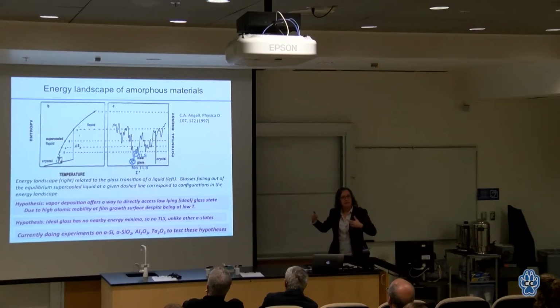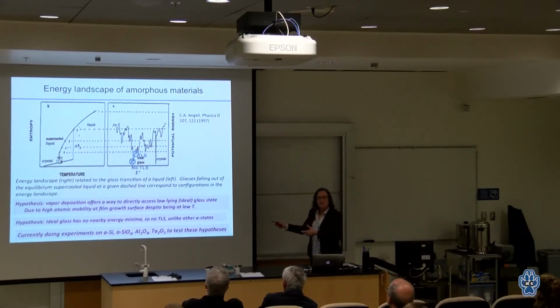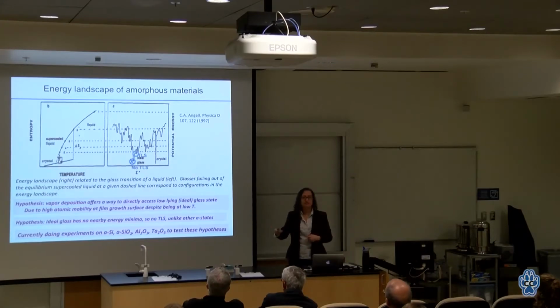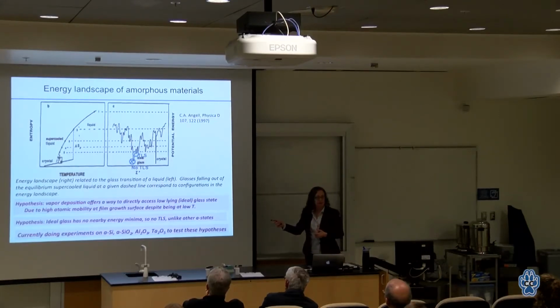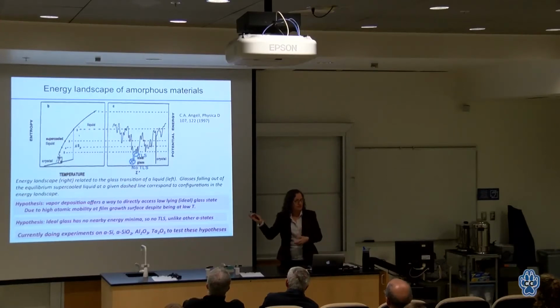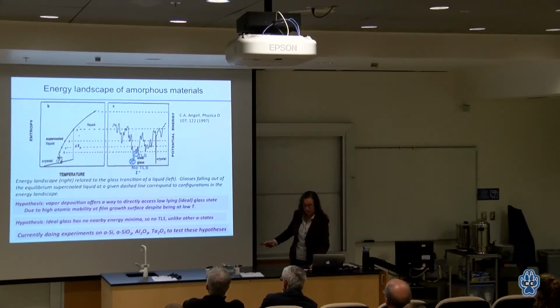Getting rid of these TLS gets rid of this extra heat capacity, but those TLS are also what led to all the losses that are bad for the LIGO detectors. So far we've only managed to get rid of TLS in amorphous silicon. They don't want amorphous silicon, they want things like silica and tantala. But the hope is that the techniques that we've developed for silicon will also apply to these other materials.